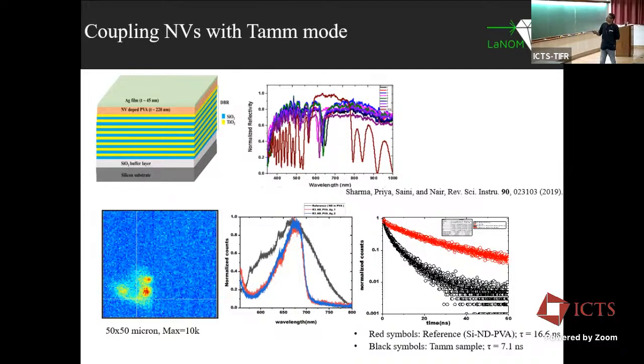We have a micro reflectivity setup in our lab, which is even published in this journal, on how you can build this setup, because you have to do local measurements. You cannot use any conventional spectrometer or anything, because the spot size should be below 5 micron or so. So we measure the reflectivity. This brown line is without any cavity, so you get the very good old DBR band gap. And when you have a metal layer, you see the Tamm mode appearing at close to 640 nanometer. And I show this spectrum very intentionally. You can see that this Tamm mode is fluctuating, it depends on where you measure it actually.